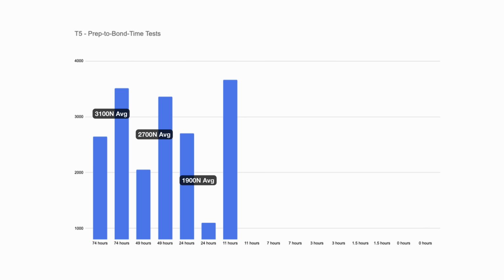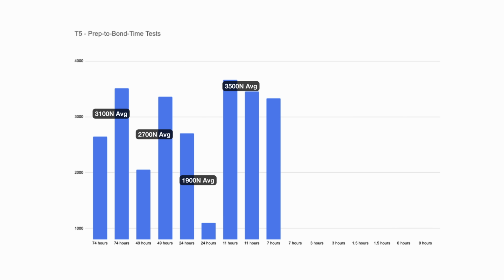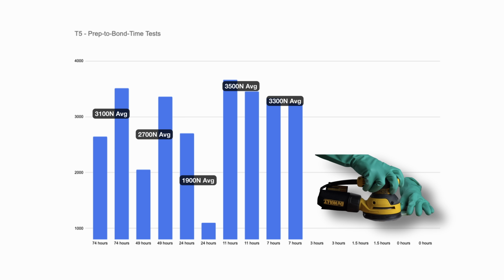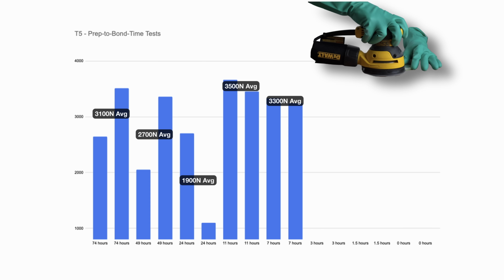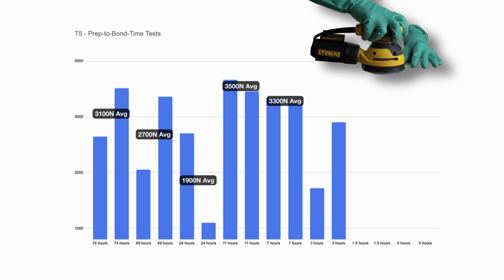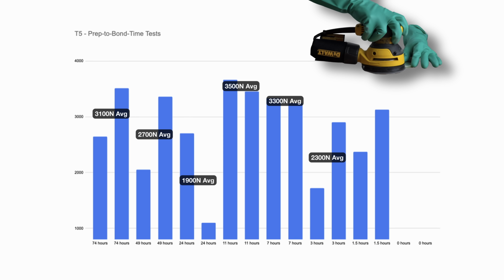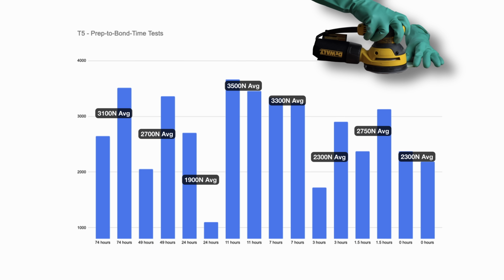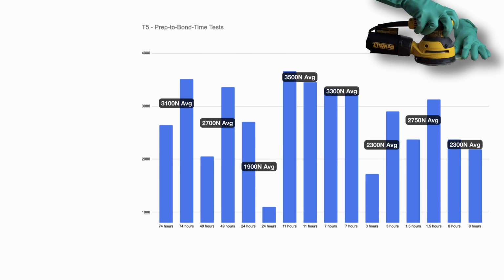At 11 hours, we have two solid results averaging about 3,500 newtons, and at 7 hours, another two strong ones averaging 3,300. At 3 hours is where I switched to the orbital sander, and we have a big split between 1,700 and 2,900, averaging 2,300. At 1.5 hours, we have a smaller split averaging 2,750, and the immediate bond test dropped to an average of 2,300. These results are very messy, but I think we can still learn from them.